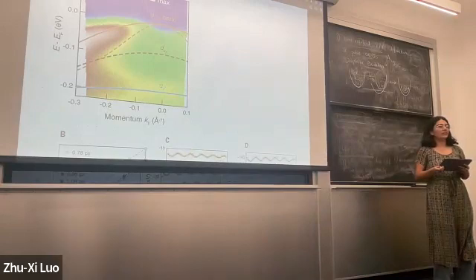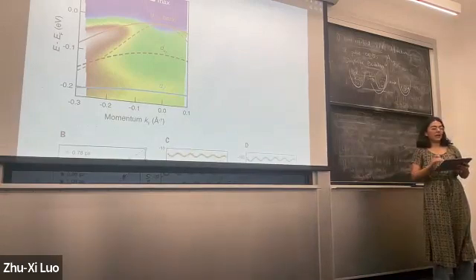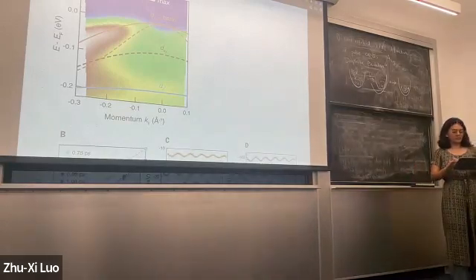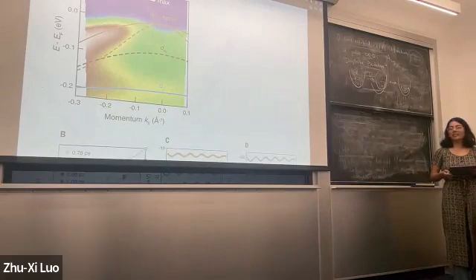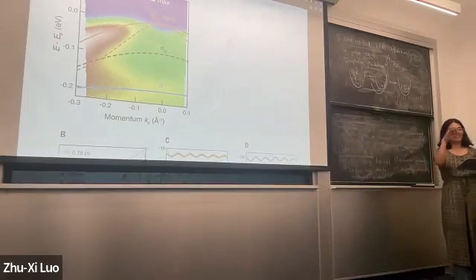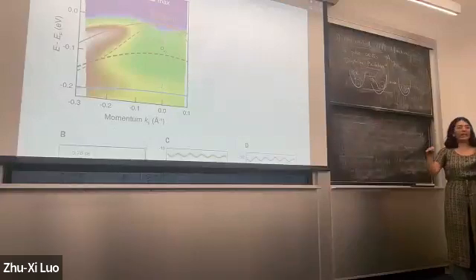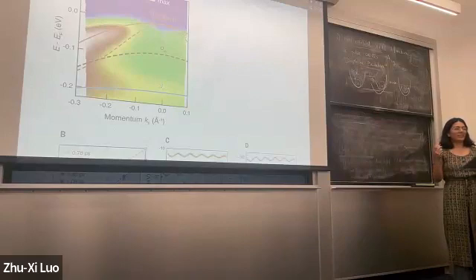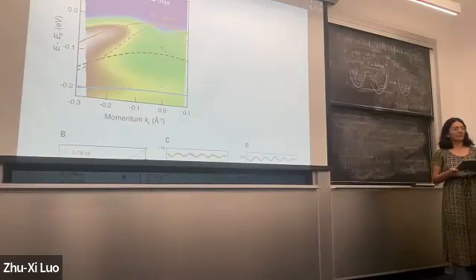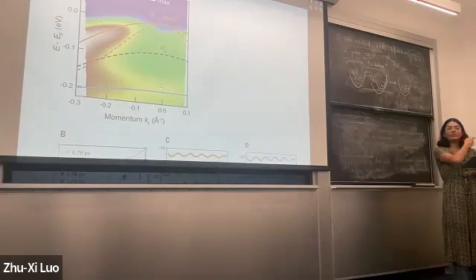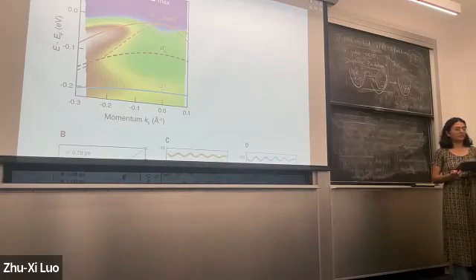In which sense are you saying that here the phonons are coherently excited? What are the incoherent excitations of phonons? Is there an example? I guess if we had some broader Fourier transform signal, then this would be an indication that you have excited a lot of different excitations with different frequencies. Here we have this very sharp peak, so we only have this mode. The decay of the amplitude presumably also corresponds to coherent excitations. Yeah, these other heating effects are examples of some incoherent things.